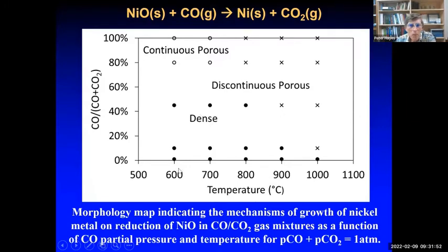So we can make maps of these different reaction morphologies depending on the reaction temperature and the gas conditions in the reaction system. So here we have CO over CO plus CO2. So in other words, the concentration of CO in the gas mixture. Pure CO at the top, no CO at the bottom. And these various marks here indicate the different types of reaction product that we see.